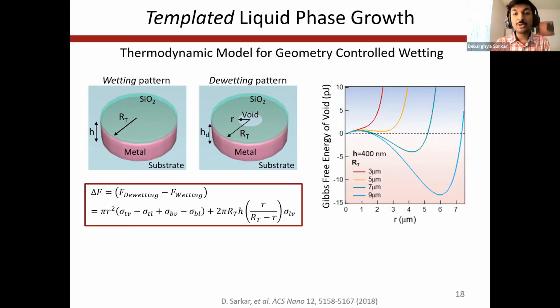In other words, thermodynamically, void formation is not possible for templates of radii 3 and 5 micron when the initial indium thickness is 400 nanometers. For the same thickness of indium, however, if we have templates 7 or 9 micron radius, then there are negative values of Gibbs free energy. In fact, there are certain energetic minima indicating that there are possible values of voids forming in these sizes, and there are certain void sizes which are most thermodynamically favored.